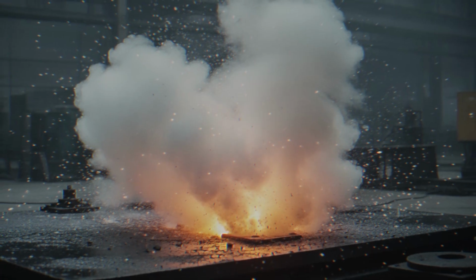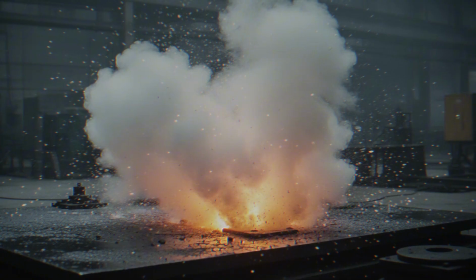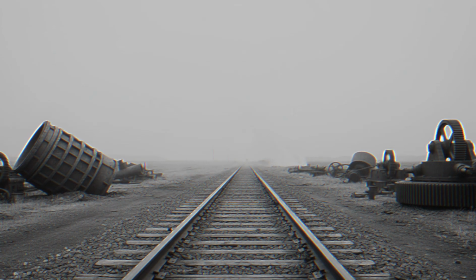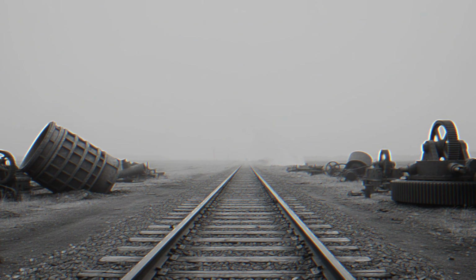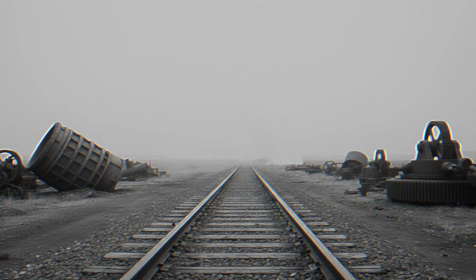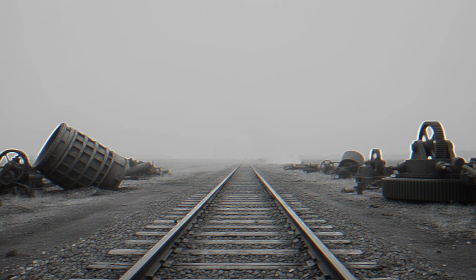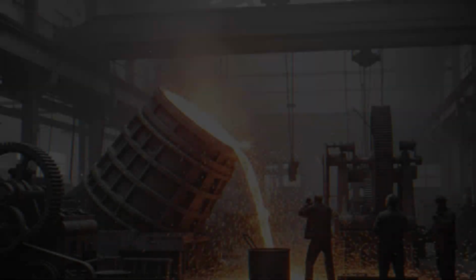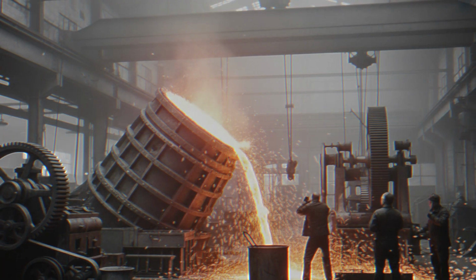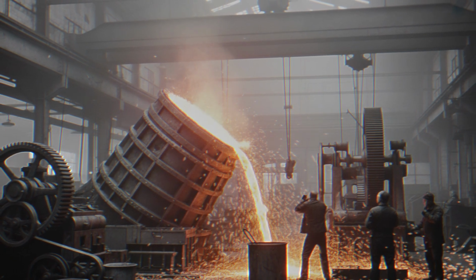The lesson is specific. These machines, as large, as powerful, as economically important as they were, were fragile in ways that the scale itself obscured. The 22-meter furnace that produced 100 tons of iron per day was held together, at a fundamental level, by refractory brick that eroded at measurable rate, by rivets that corroded in hidden sections, by bearings that needed manual attention on a schedule that could not be missed.